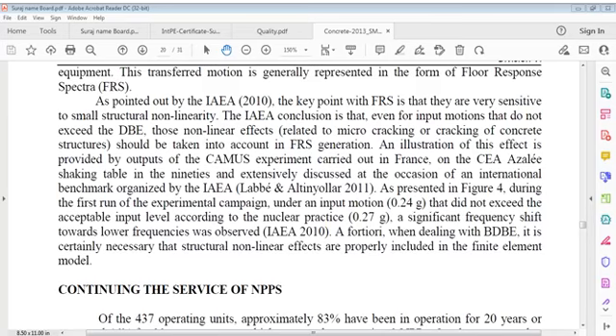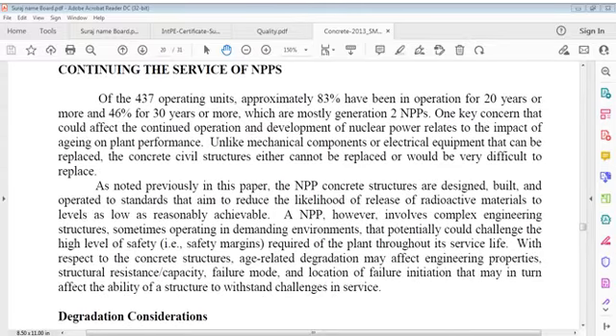During the first run of the experimental campaign, under an input motion of 0.24 g that did not exceed the acceptable input level according to nuclear practice (0.27 g), a significant frequency shift towards lower frequencies was observed. A fortiori, when dealing with BDBE, it is certainly necessary that structural non-linear effects are properly included in finite element models of NPPs.